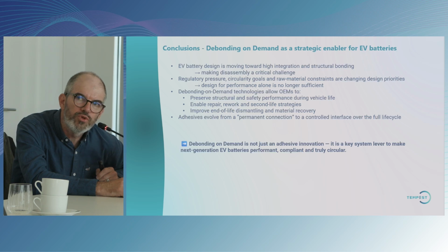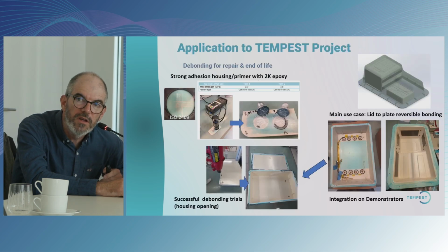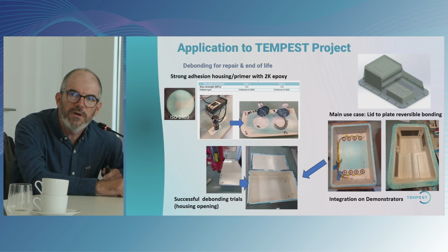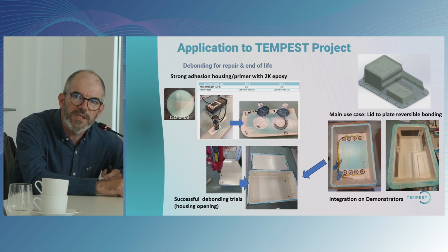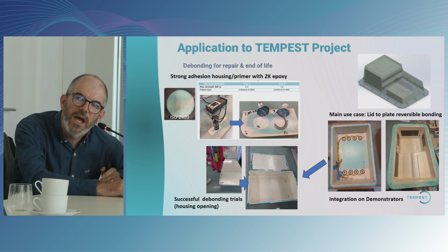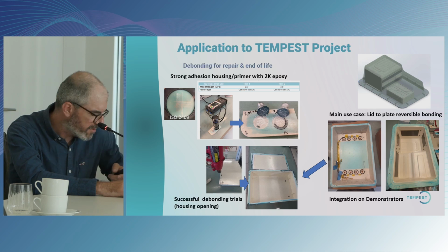In the end, we were able to do the debonding very easily with a simple tool. As I told you, the idea is to use a very simple tool because we use a hot gun. You cannot use a robot, which is a very complex system, because in the end, the OEMs want to do it in very cheap conditions. So we decided to test with a hot gun, and we got very nice results, easy debonding and a maximum temperature very close to the bond line of 90 degrees C. It means that at the component level, we would be at not more than 80 degrees C, so quite okay with the maximum service temperature we had in the specifications.